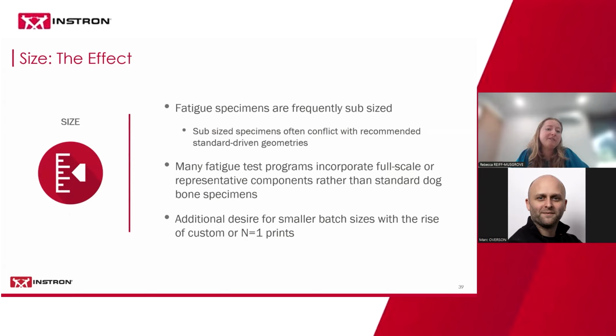Beyond that, we also see many fatigue test programs actually incorporate full-scale or perhaps representative components in their testing. So rather than a sample that looks like a standard dog bone, you get a sample that can look like anything, a part of an aircraft, a part in a human body. An additional effect with this size is we're also seeing a desire for smaller batch sizes with the rise of custom prints or even N=1 prints. You know, why would anyone want to test 30 specimens when they're actually only making one instance of that print, perhaps a super custom part that has been designed, for example, for biomedical use?